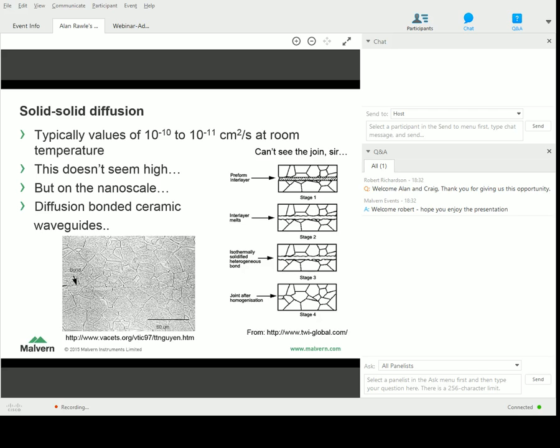a 20-micron hole in a foot of ceramic material, and you couldn't do that by drilling, so you'd have one surface in which that trench was carved at 20 microns. You'd have another surface. You'd have them very flat, and you just push them together. And in a ceramic material, the diffusion between the particles would cause the two layers to bond together. And these very flat surfaces, of course, but you'll see that's a route to producing something that would be otherwise very difficult, a 20-micron hole in a foot of ceramic.